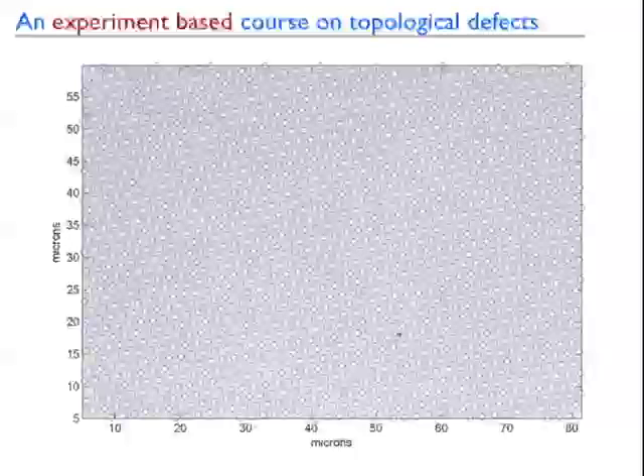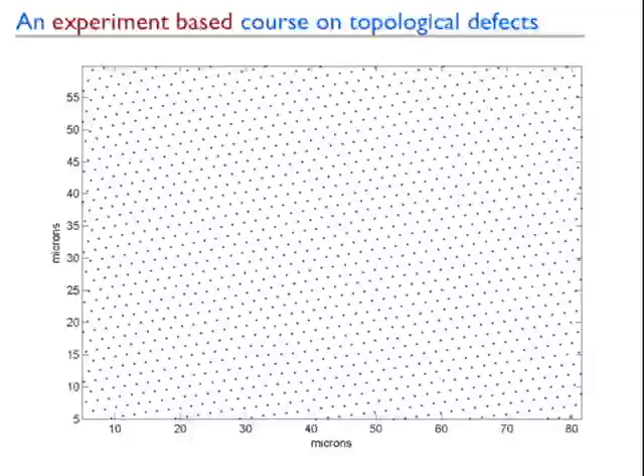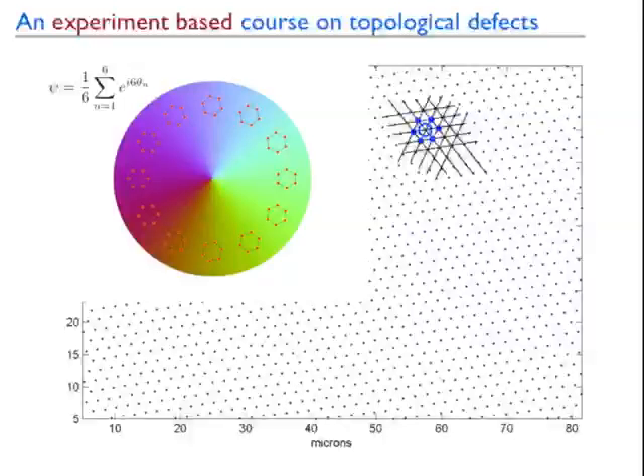You threshold this guy. You use software to locate the centers. You can locate the lattice. You find the neighboring particles in the lattice. You do a Delaunay triangulation, and then a Voronoi construction to find out the coordination of each guy. You expect a hexagonal lattice, and you get a hexagonal lattice here. You look at the orientation to see whether there are strains in the system or whether it's a nice uniform crystal by coloring according to orientation.